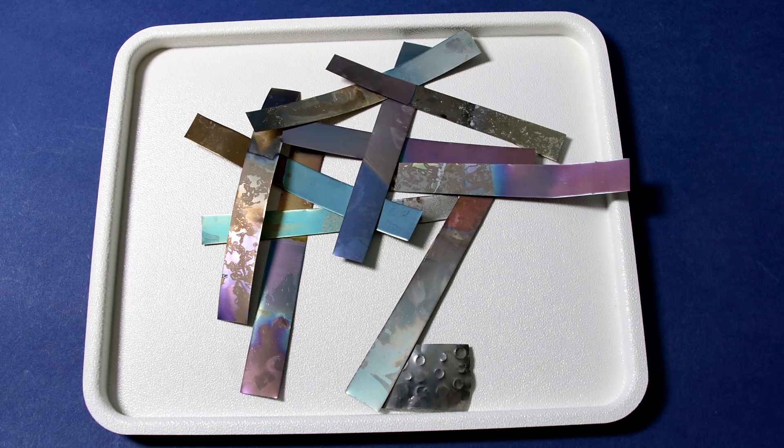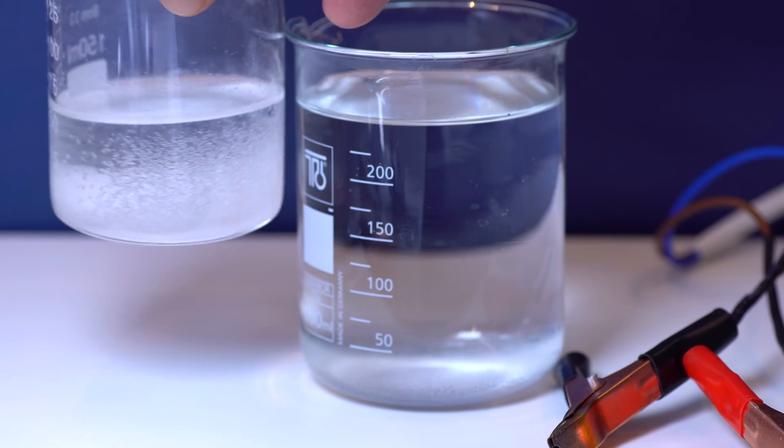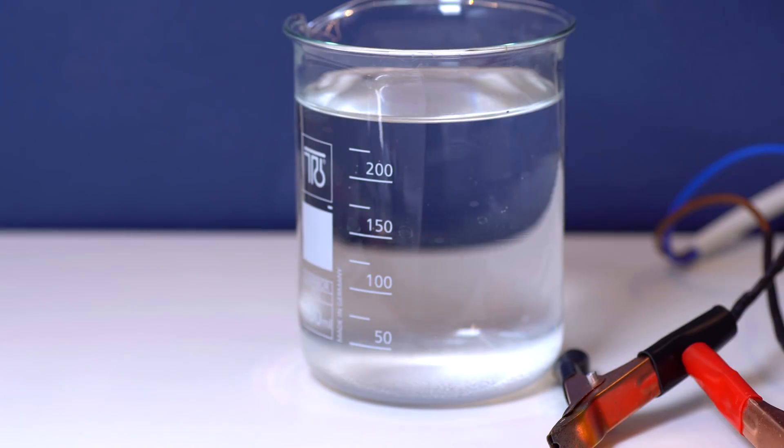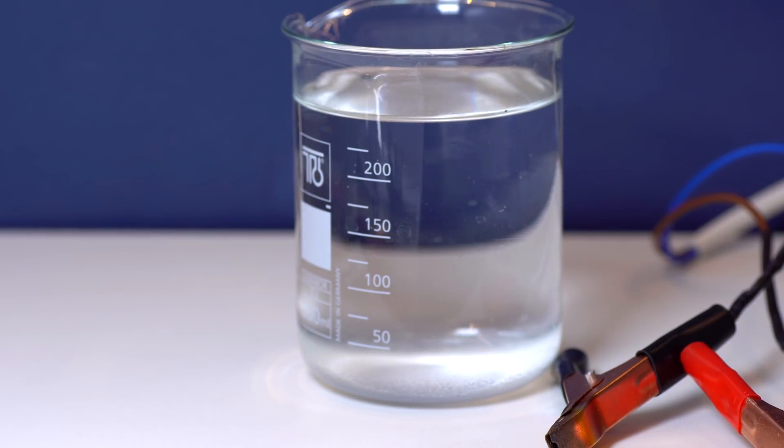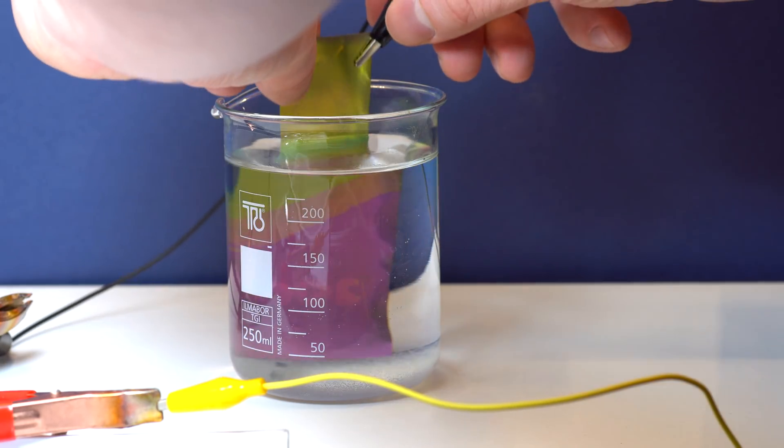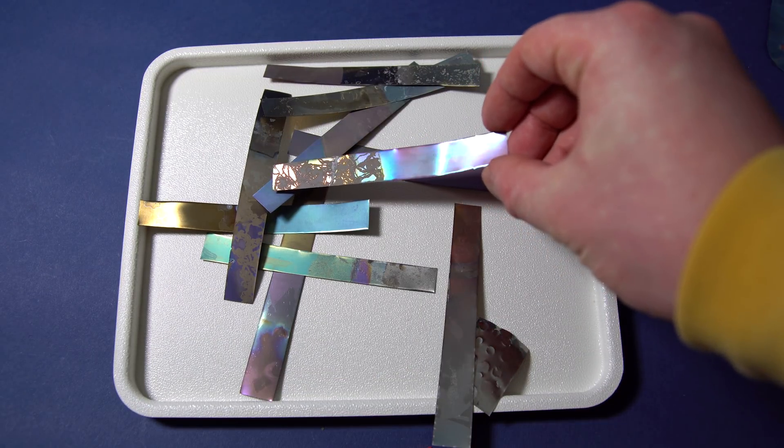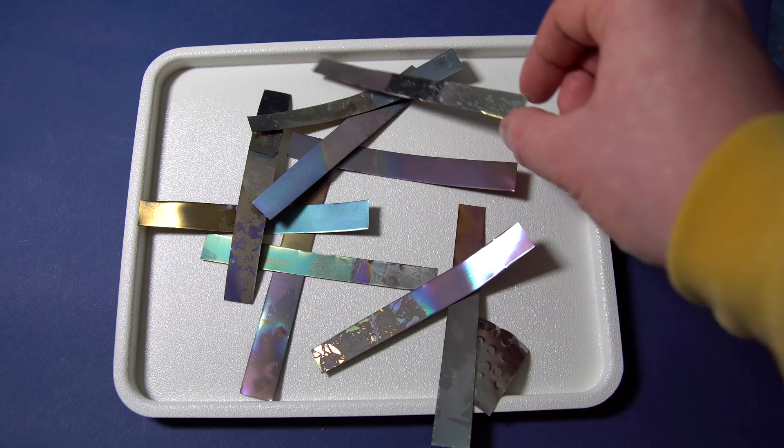After several unsuccessful attempts, I finally made a more or less working electrolyte, which is a solution of sodium tetraborate, or simply borax. Concentration here is about 2 grams per 100 milliliters. Apart from borax, solution of an ordinary soda is also suitable.